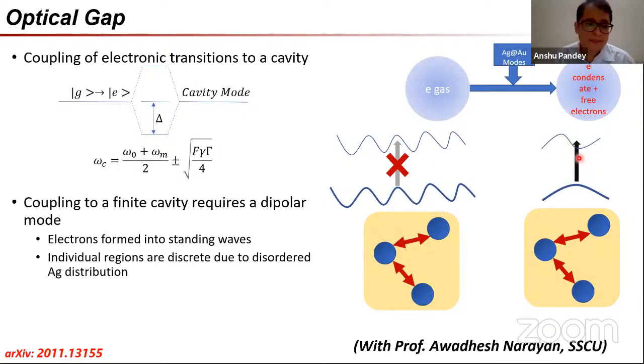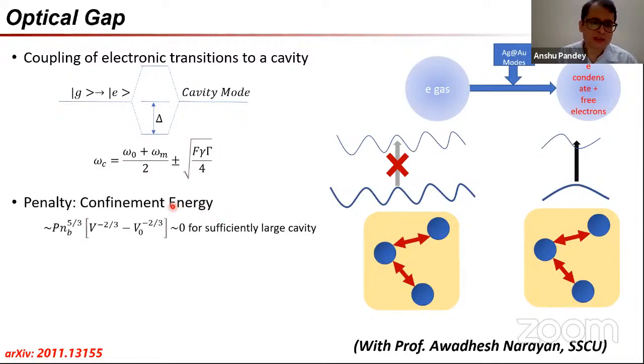Now, the point is, why would electrons localize in such a system? The reason is, firstly, the argument against it is that there would be a confinement energy penalty. But again, such penalties would vanish if we are dealing with a localization length which spans several silver clusters, which would be around 10 nanometers. Beyond 10 nanometers, we wouldn't really be caring about confinement effects. So there's no penalty for localization, but at the same time, there's also no motivation.